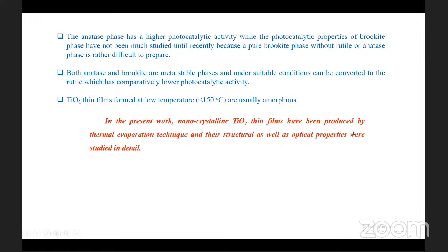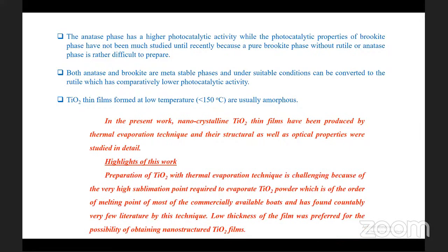In the present work, nanocrystalline TiO2 thin films have been produced by thermal evaporation technique, and their structural as well as optical properties were studied. The main highlight of this work is preparation of TiO2 with the thermal evaporation technique, which is challenging because of the very high sublimation point required to evaporate TiO2 powder, which is of the order of the melting point of most of the commercially available boats, and very few literature reports exist on this technique. Low thickness of the film was preferred for the possibility of obtaining nanostructured TiO2 films.